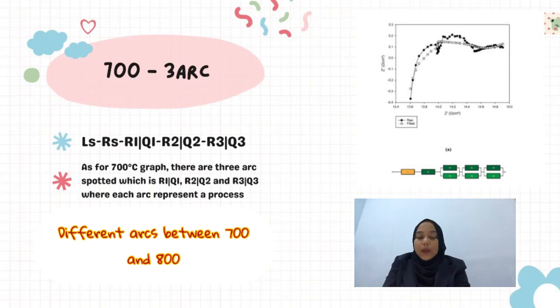Area specific resistance is then calculated by using the formula Rp times S divided by 2, where Rp stands for polarization resistance at the interfacial layer of cathode and electrolyte, and S is the surface area of the pellet. The polarization resistance Rp is also defined as the sum of R2 and R3.